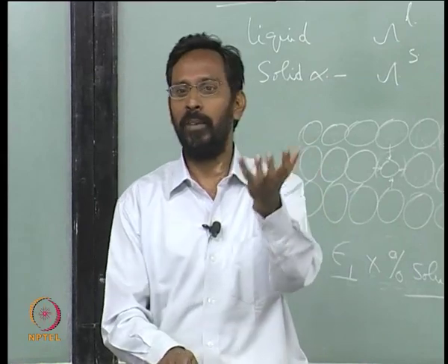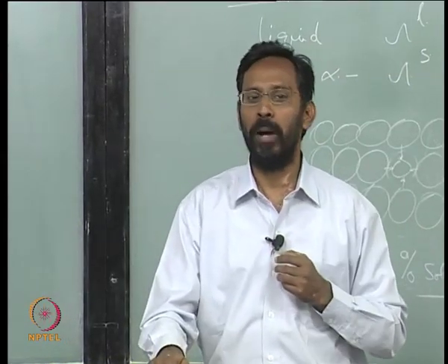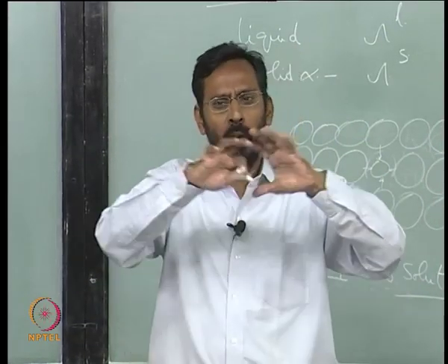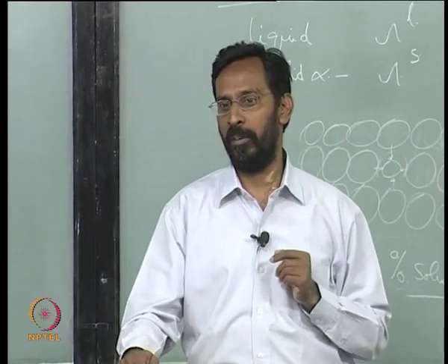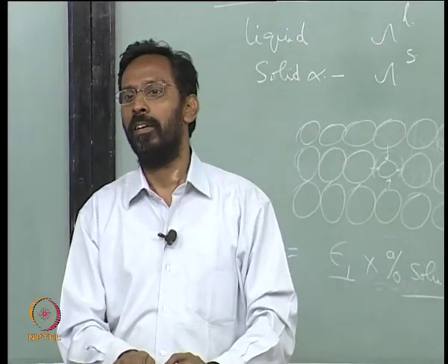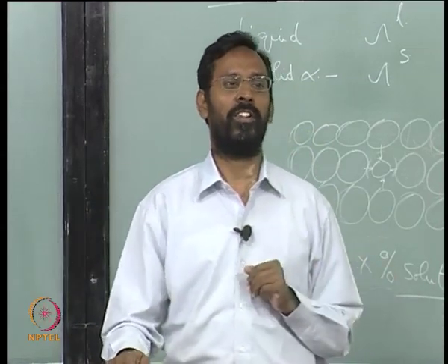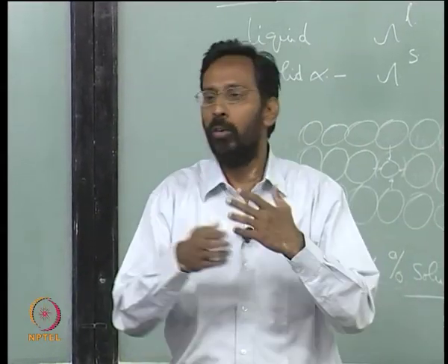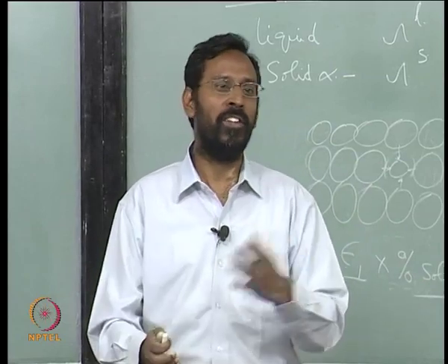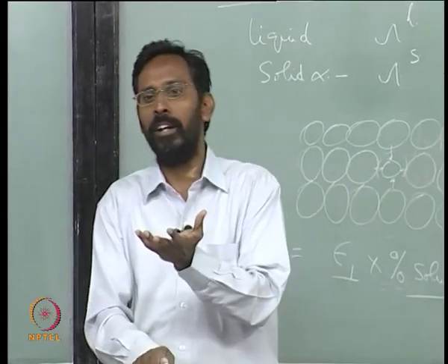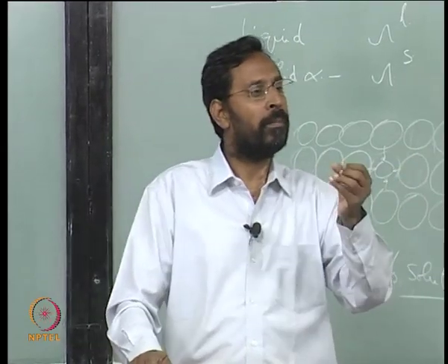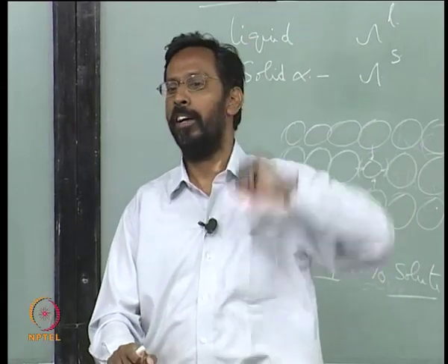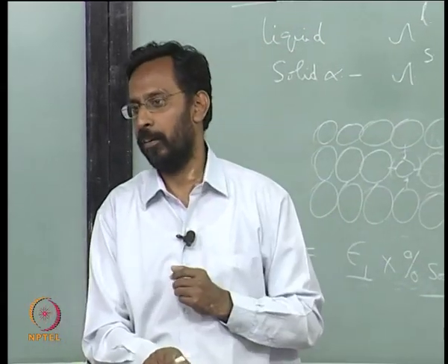This structure, when they have put it into such a high voltage microscope, with more and more dosage of this electron beam, they saw that slowly this ordered structure becomes a disordered structure. That means the superlattice changes into a disordered structure. That means whatever superlattice reflections you usually see in an ordered structure, they slowly start vanishing. In situ you can see this in a TEM. So keep on observing how the diffraction pattern changes. You see that superlattice reflections slowly vanish and only the fundamental reflections you see. That means the ordered structure has become a disordered crystal structure, but still it is